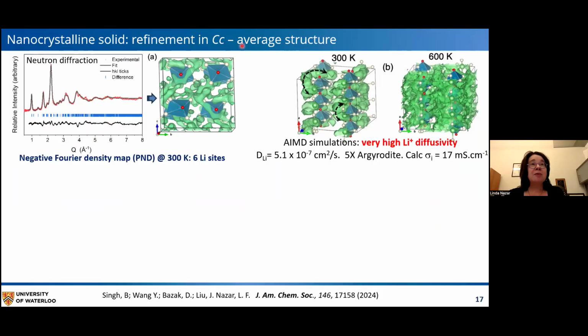And we carried out our refinement in the Cc space group, unlike what they did, because, as I said, this is an average structure. And from the negative Fourier density map, which is specific to the negative scattering length of lithium, we were able to identify 6 sites, which are shown here, of the 8 that were predicted in the lattice. And we carried out AIMD simulations, and these show really very high diffusivity.